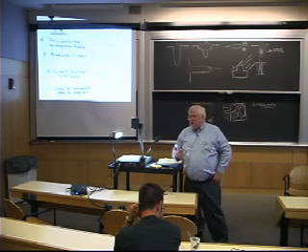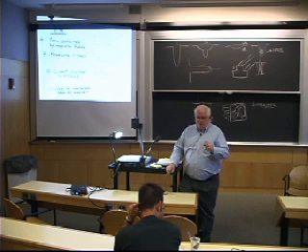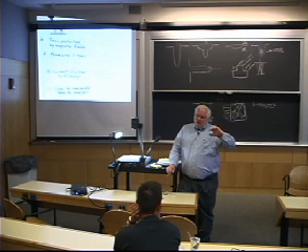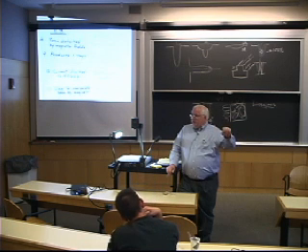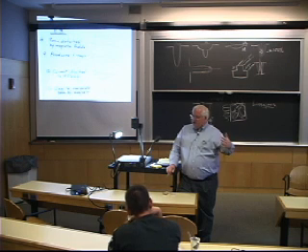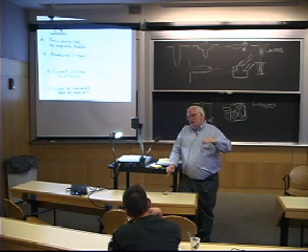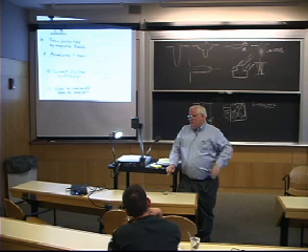Well, it turns out that's sort of a contradictory thing for a material, because in order to have good thermal conductivity, you usually want good electrical conductivity in a material. Good electrical conductivity means it reflects the laser. I want to absorb the laser but have good thermal conductivity, and they usually go together. In fact, there's something called the Wiedemann-Franz law, a relationship between thermal and electrical conductivity. It says that they're correlated.